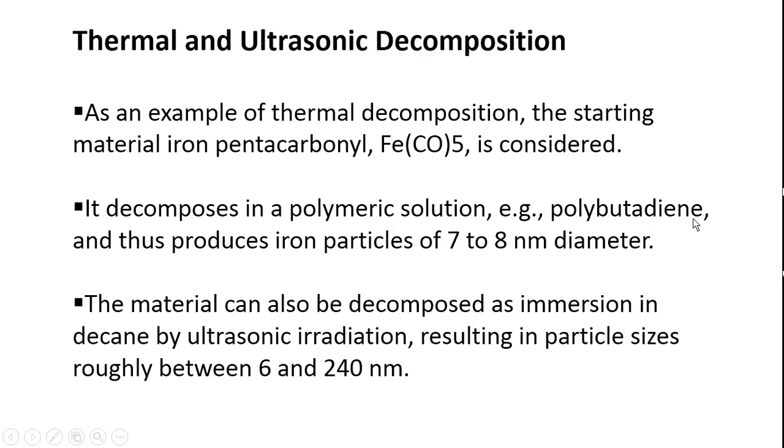The polymeric solution will be combined with this iron pentacarbonyl, and they react with each other, producing iron particles of 7 to 8 nanometer diameter.